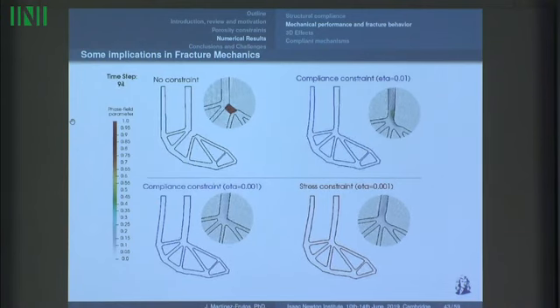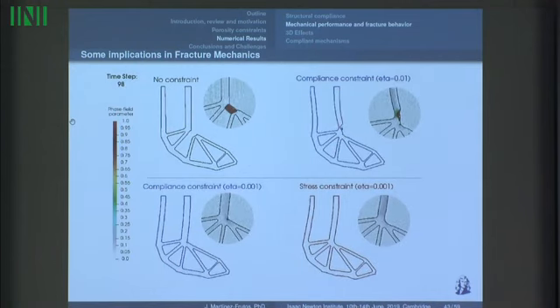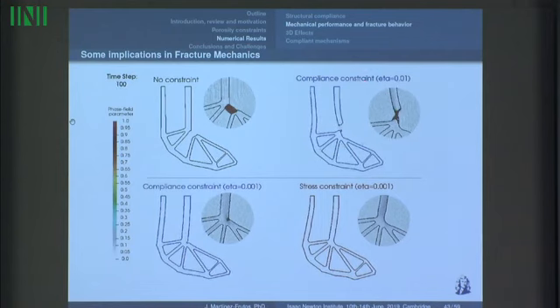Then the other designs that fracture in these numerical experiments are the design with the compliance constraint, the porosity constraint in compliance with these two values of eta. So notice that for this value of eta, the design has broken a bar, and in this design the fracture just has initiated. In the case of a stress constraint, we don't have a fracture for this load.